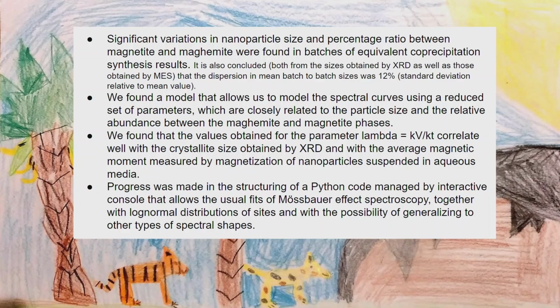And they are closely related to particle size and relative abundance. So one can talk about what is bigger, what is smaller, or what is more maghemite-like or more magnetite-like. We found that the values obtained from the parameter lambda correlate well with the crystal size and also with the magnetic moment obtained from magnetization.